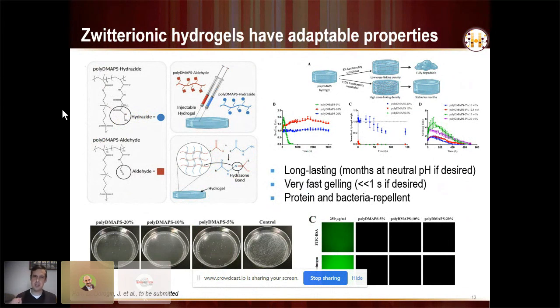But here, there's particularly interesting properties because the zwitterionic hydrogels, when they're far enough apart, we see a lot of water. That charge separation is so close between the positive and negative charges, it kind of blurs. We start to bring the polymers closer together in a cross-link structure, though. There's still discrete positive and negative charges in each monomer unit. And we get electrostatic interactions which actually can support the covalent hydrazone cross-linking.